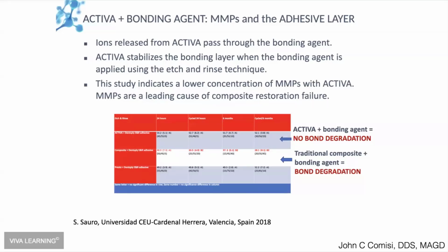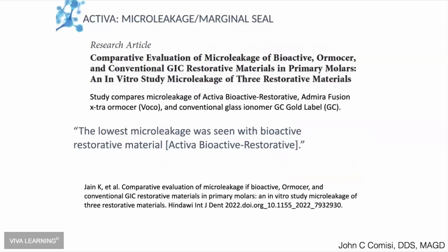And a lot of people say, but if you're putting a bonding agent down, doesn't that prevent the ions from penetrating into the thing? Well, we have to look back at this: after about 30 days, the immediate bond strength of our bonding agents starts to fail because of the water permeability situation. So as the moisture and the semi-permeability of these bonding agents, which originally were non-permeable, occurs, as we've seen in many studies, the ions that are present can then penetrate and help to form crystals, which on the superficial aspect can be extremely beneficial in trying to curtail and stop any kind of breakdown that's occurring.